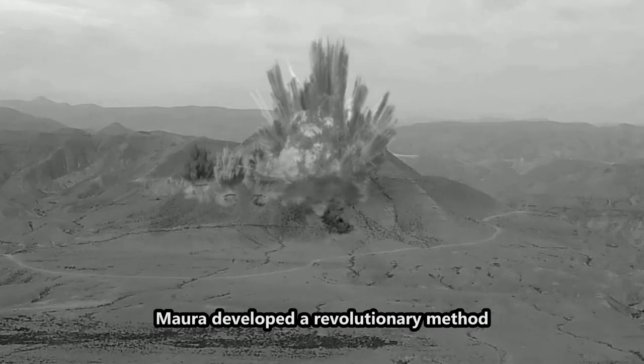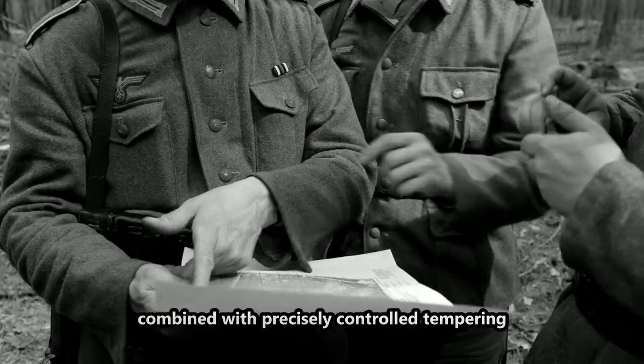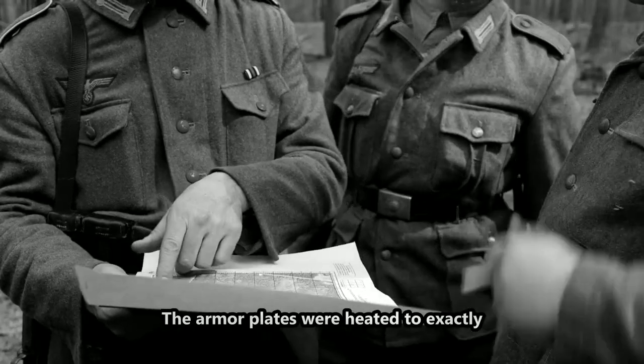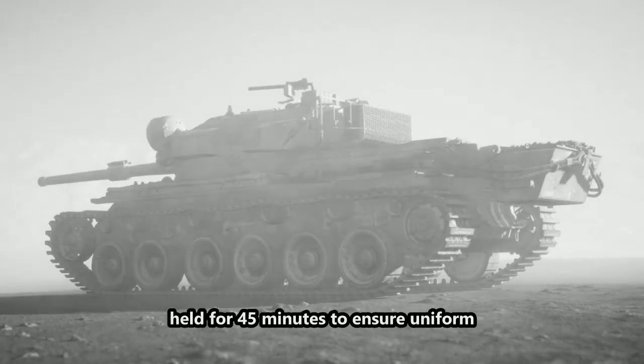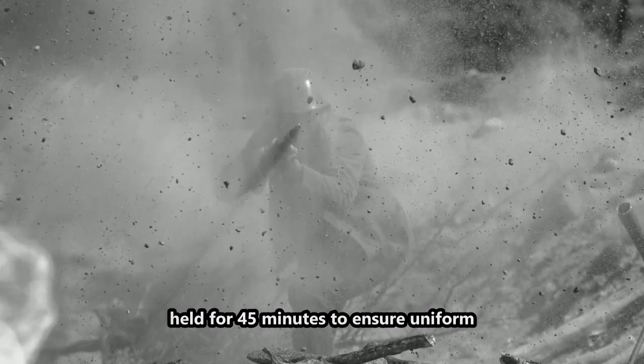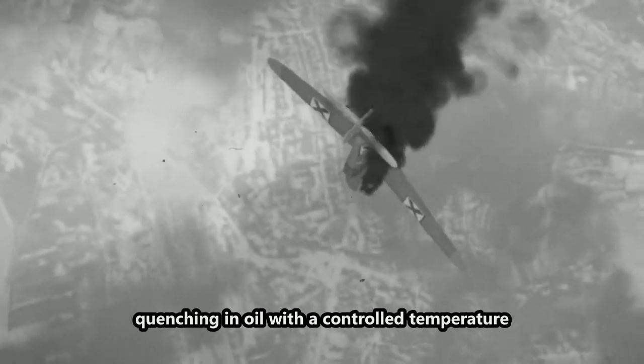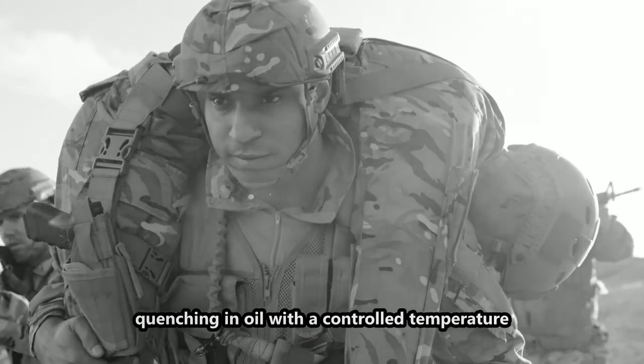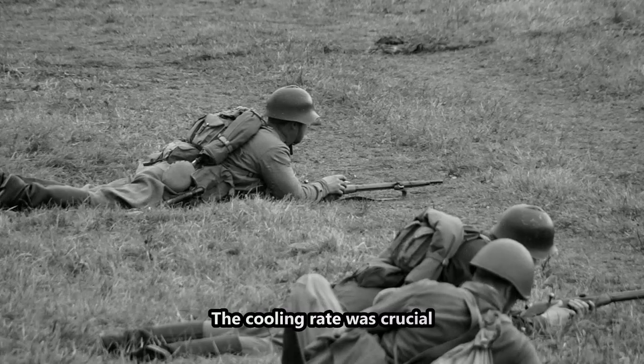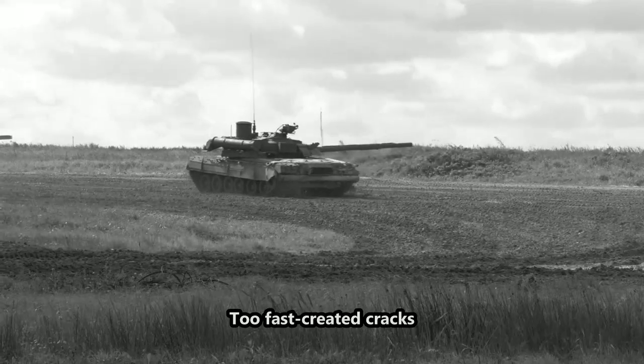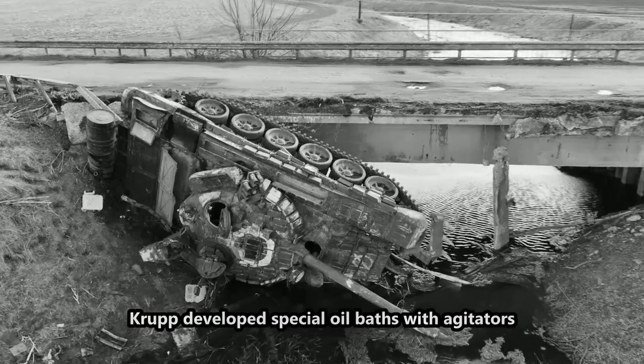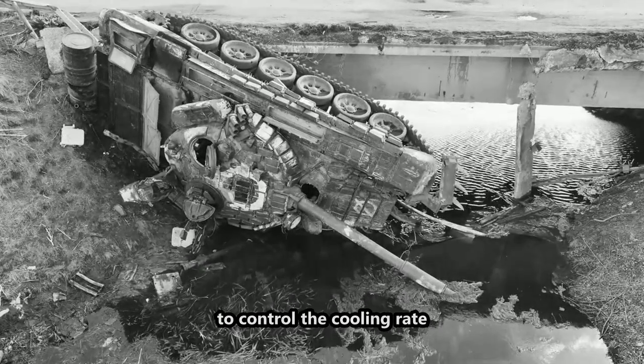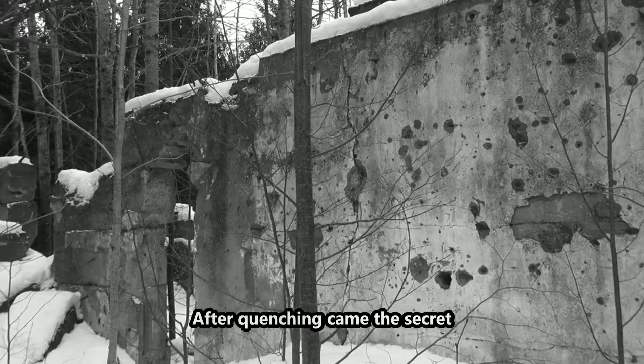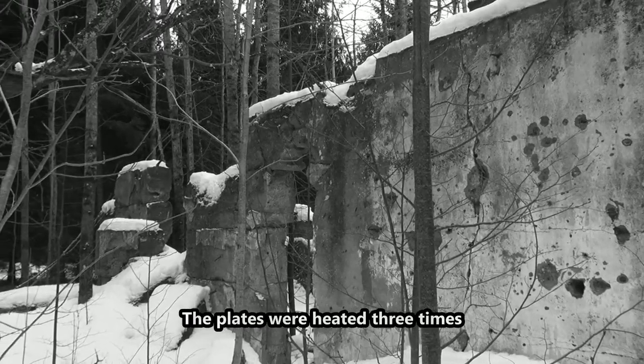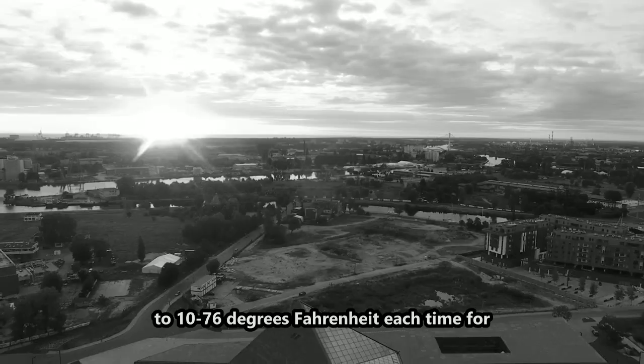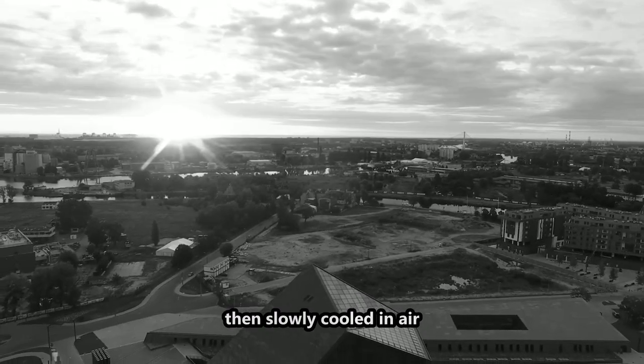Maurer developed a revolutionary method: differential hardening combined with precisely controlled tempering. The armor plates were heated to exactly 1550 degrees Fahrenheit, held for 45 minutes to ensure uniform austenitization. Then came the critical step: quenching in oil with a controlled temperature of 140 degrees Fahrenheit. The cooling rate was crucial. Too fast created cracks, too slow prevented complete martensite formation. Krupp developed special oil baths with agitators to control the cooling rate precisely. After quenching came the secret: multiple tempering. The plates were heated 3 times to 1076 degrees Fahrenheit, each time for 2 hours, then slowly cooled in air.